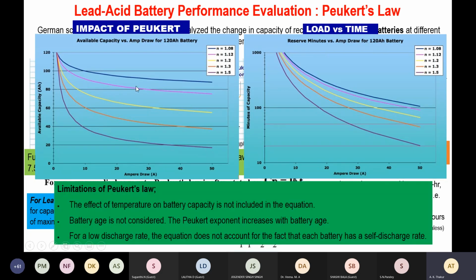The limitations of Peukert's law: the effect of temperature on battery capacity is not included, which is very crucial in the case of lead acid cell, because if we increase temperature, first water of the electrolyte evaporates, and second, electrolyte density becomes thin, that affects capacity drastically. Battery age is not considered in this case because Peukert's exponent increases with battery age, and this is another limitation. And for a very low discharge rate, this equation never accounts for the fact that each cell has a self-discharge rate.